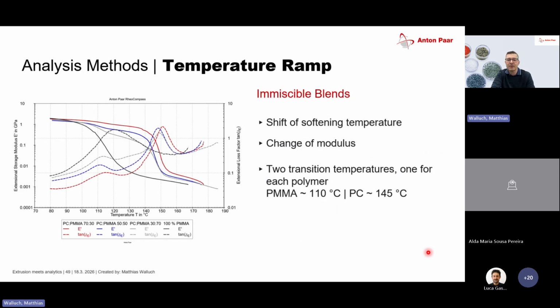I just want to give you an insight in material behavior on the example of the PC PMMA mixtures. We can see here again, the black curve is PC, and we can see that PMMA starts to get softer at around 100 degrees, 110 degrees. And the more PC we add, we see that we shift all this softening to a right side, so to higher temperatures.